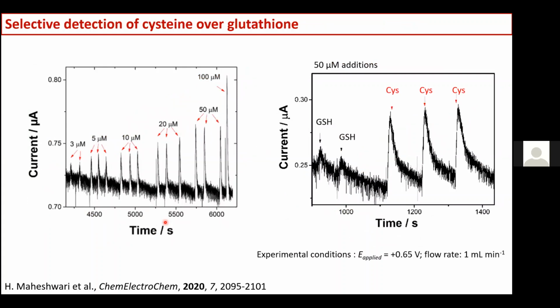So then we placed the electrode in a flow cell, and we did some injection of cysteine ranging from 3 micromolar to 100 micromolar, and we could see that we had an increase in the current recorded. And then when we were doing addition of glutathione and cysteine, we could see that for 50 micromolar of glutathione, we had a peak that was barely going out of the noise, whereas with cysteine we had a much stronger signal. So this showed that we could induce some selectivity to the system based on the size of the pore and on the reaction that was occurring inside the film.